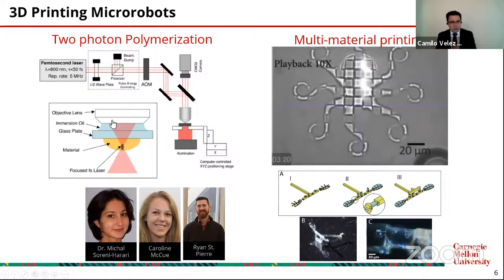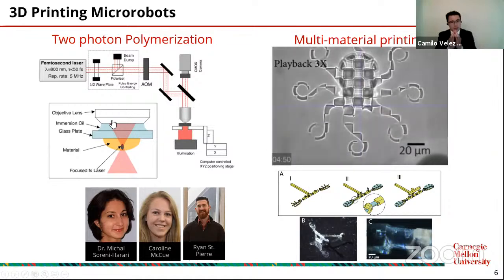The state of the art, the most used one, is the 2-photon polymerization technique. And this is the one that you can find in Nanoscribe as a 3D printer. This 3D printer uses a laser, and as I mentioned, the 2-photon polymerization technique tries to combine a voxel of light, and the polymer is going to be cross-linked, or polymerized, only in that region. And that voxel size is, generally speaking, 250 nanometers in depth, and a height of around 1 micron. So that will give us the versatility to make very small machines.